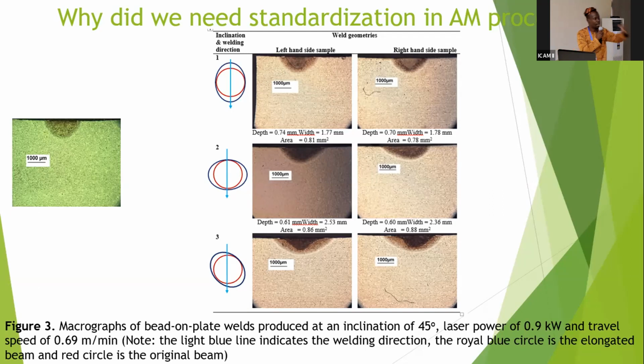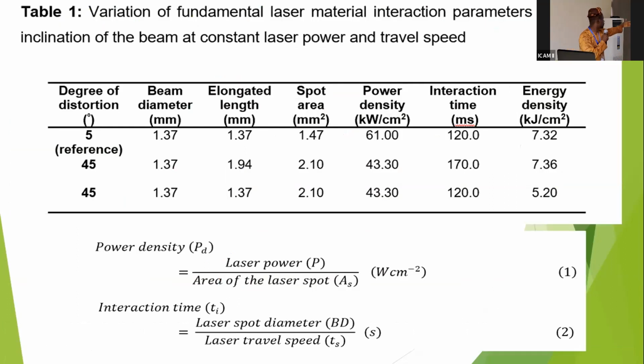Which means when you are building parts in additive manufacturing, there is a very high possibility that you will not be able to get consistent, the same tracks. The issue, from our own view, is that a laser should be designed in such a way that the optical system that goes with the laser can modify the shape, so that at every point the laser retains the same profile. What I just showed you is the parameter that I used for that. The beam spot is 1.37 when it is at 90 degrees. But by the time you move, it has increased in size to nearly 1.94 at an angle of 45 degrees.